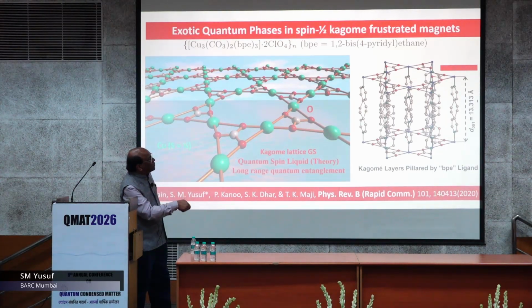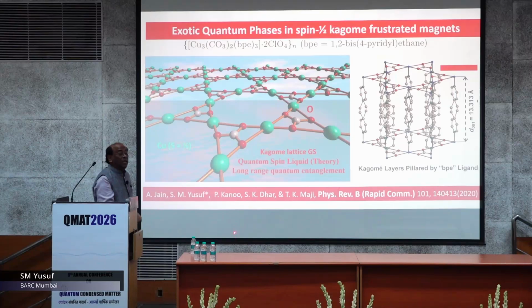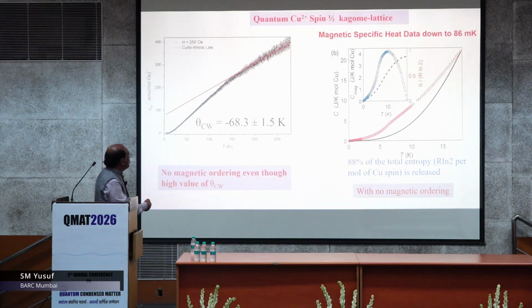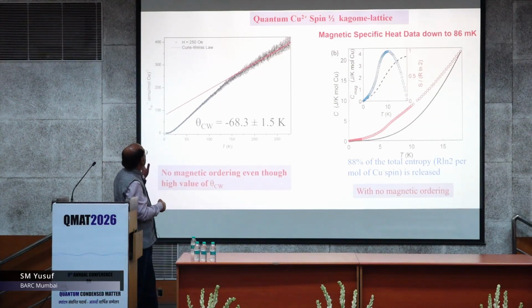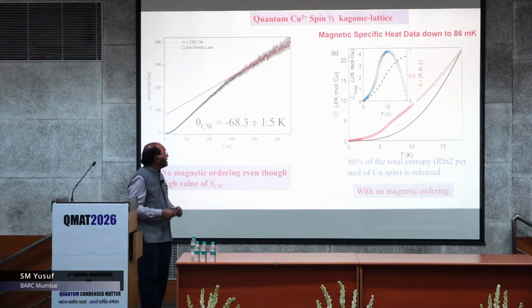Interesting is that these two Kagome layers are separated by non-magnetic so-called BPE strips, and that separation is 13.3 angstrom. So that means you can expect that this system is effectively a 2D magnetic Kagome layer, because magnetic exchange cannot propagate through this much distance through these non-magnetic ions. And what you see here again is this theta, highest temperature, minus 68 Kelvin, so quite large, but there is no magnetic ordering. So this is, as I said, very large.